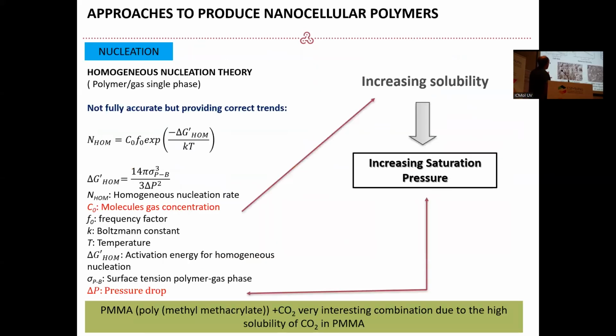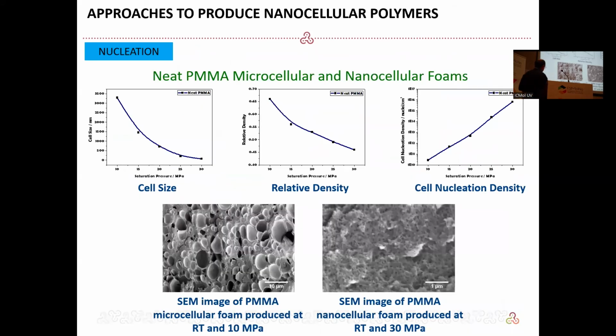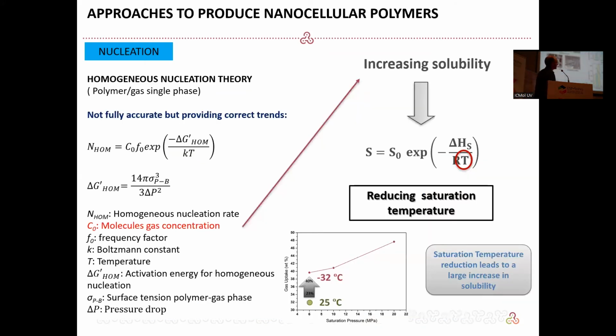So this is homogeneous nucleation. In homogeneous nucleation, we can move from microcellular structures to nanocellular structures just by increasing saturation pressure using PMMA and CO2. Very simple. The only problem is that you need a very good pressure vessel supporting very high pressures. But if you have that pressure vessel, this is very easy. So you move from 10 MPa, microcells, to 30 MPa, nanocells.